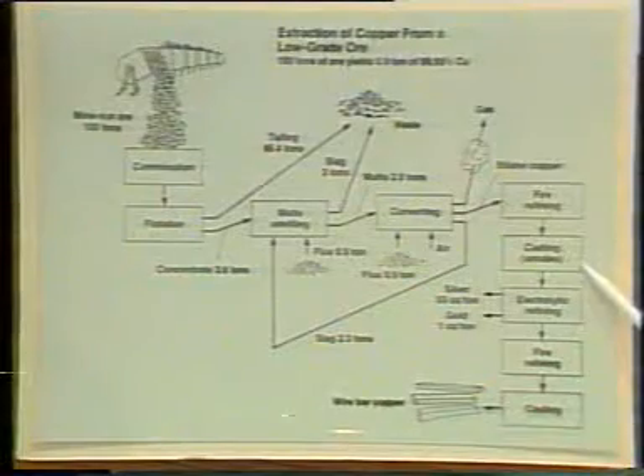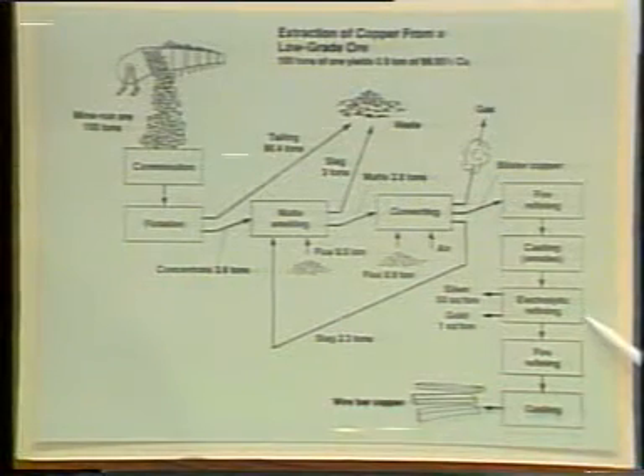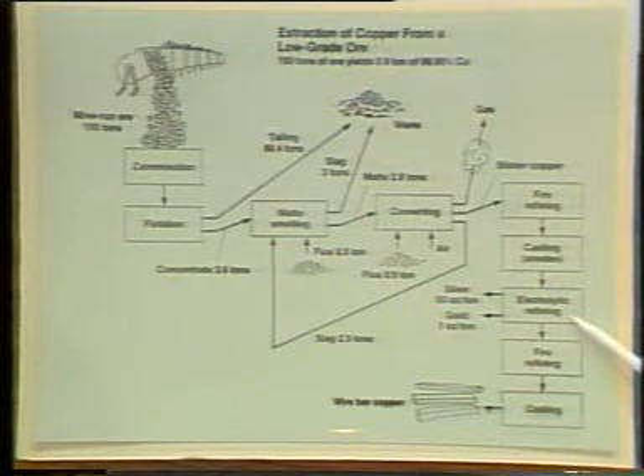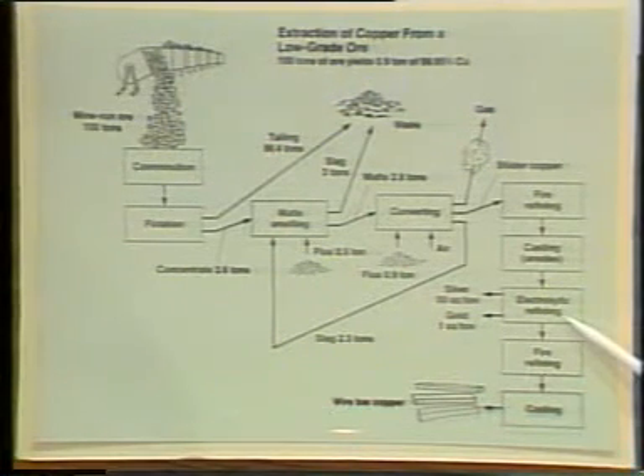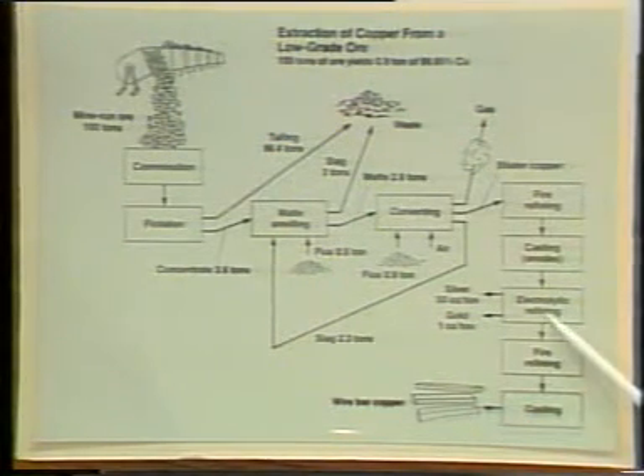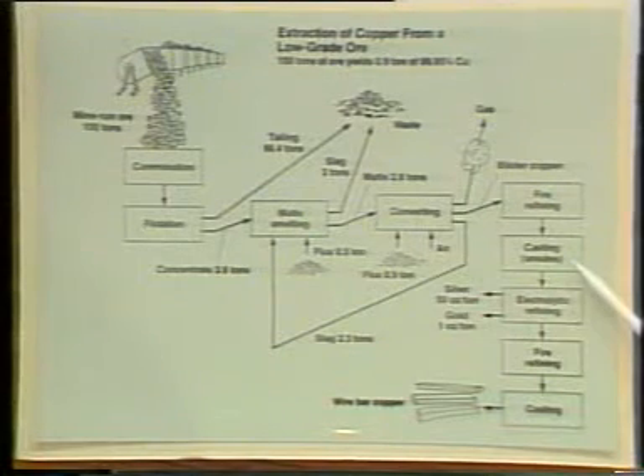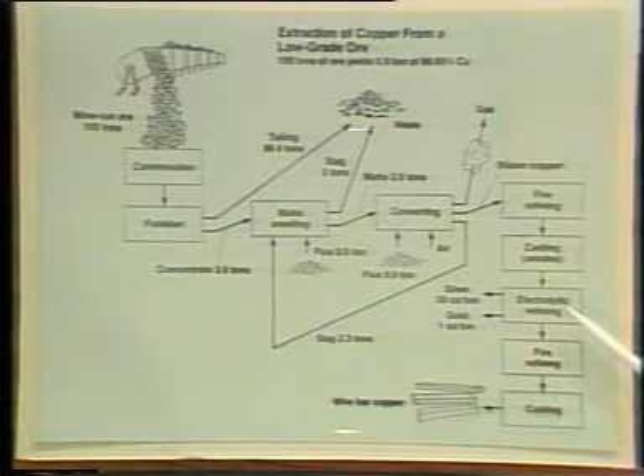Electrolytic refining plant that may be as big as an acre. We hang them in sulfuric acid containers, and in between each one of these anodes that we hang, we put a starting sheet of pure copper that we've gotten down the line as pure copper. And then we pass a current through it, and we get plated from the anode, which is impure, to the